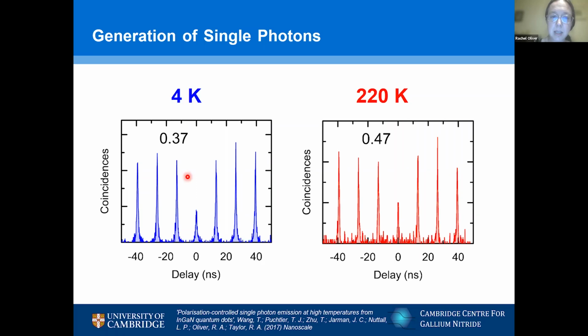And we can see this dip in the Hanbury Brown and Twiss trace. And the same for the data recorded at 220 Kelvin, a much higher temperature. And again, we have a dip. Now, two things to note about this data. I said we would like there to be a dip down to 0, and we've got a dip down to about 37% of the average of the surrounding peaks.